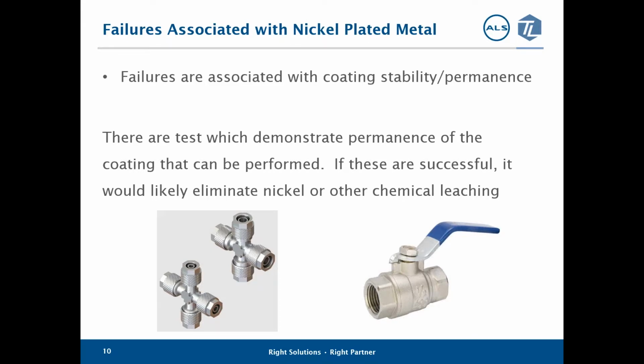For nickel-plated products, failures related to the lack of coating permanence is the main cause of failures. There are tests that can be done by manufacturers to assure a coating will be permanent and the nickel coating does not come off. These tests should be performed by the manufacturer.